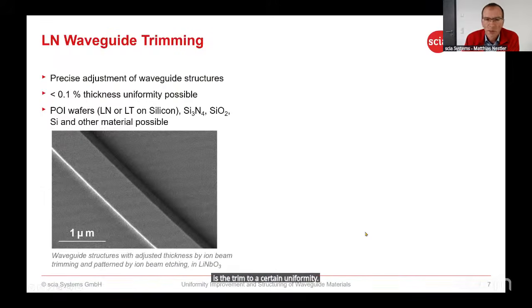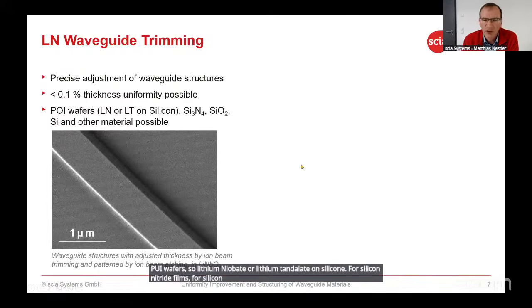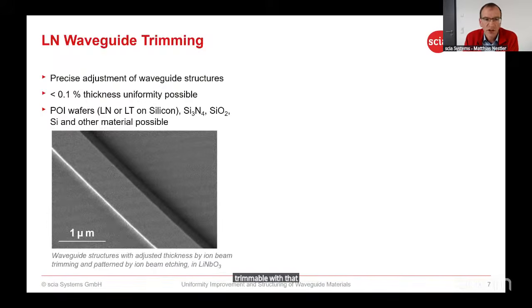This can be applied for POI wafers, so lithium niobate or lithium tantalate on silicon, for silicon nitride films, for silicon oxide films, or silicon films on silicon oxide or SOI wafers. All these materials can be trimmed. Even other materials are trimmable with that principle. We achieve uniformities of 0.1% and better.